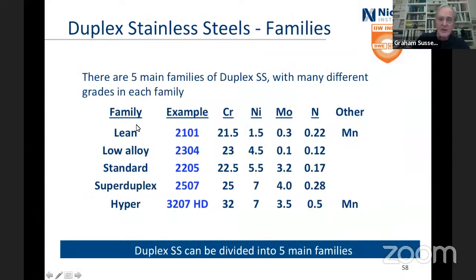There are these families, and look at the variation going down here. We're increasing, well, generally increasing the chrome. The nickel, very, very low there because it's nice and cheap. And then we're getting more and more nickel up here because the chrome is actually trying to drive it to be all ferritic. And if you start adding moly, then it gets even worse, because that and that is going to try and make everything ferritic. And so you add nitrogen.